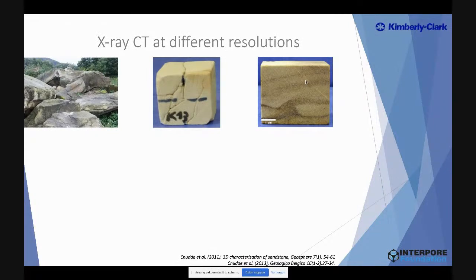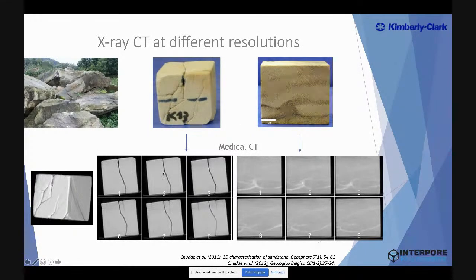So here you have an example of two Belgian sandstones, and you see that their dimensions are a few centimeters, and you immediately see macroscopically some fractures, and also some layers which are more iron rich. So if you put those in a medical scanner, you will see the fractures in 3D, so you can follow those clearly, and you can also see where you have the iron-rich layers, which have a higher contrast compared to the quartz layers in between. So this is already giving important information on the structure and composition of your material.